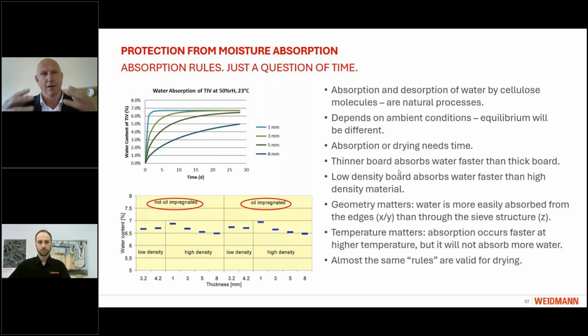So you can impregnate it, you can increase the density, you can increase thickness, you can increase whatever you want, but sooner or later, if you leave them out without any packaging, without any secure storage, just in ambient condition, in a couple of days or weeks, depending on the thickness, density, and the properties of the material, you will have almost 6-7% moisture inside of your paper and board.